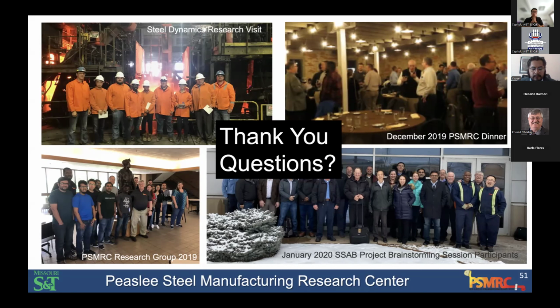We have certainly thought about this a lot, and a number of people have been concerned about what happens in the presence of water vapor in a system, not only in hydrogen steelmaking, but hydrogen combustion, right? Or hydrogen reheating, for example, particularly in reheat and tunnel furnaces. And what I can tell you is, if you look at the water content of hydrogen, of course, the product is 100% water, but the water contents are still pretty high in natural gas. You've got four hydrogens to the one carbon, right? Typically. And so even there, the water contents are high.